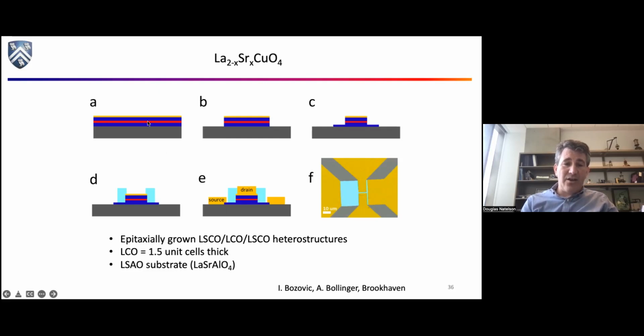So you can take your 3-layer thing, you can coat the top of it with gold, you can carve it into basically a mesa. You can put some insulating layers around it just to make sure you don't accidentally short the top to the bottom. And you can contact the top electrode of this mesa and the bottom electrode separately. And now you've made a tunnel device. And here's a kind of a false color electron microscope image.